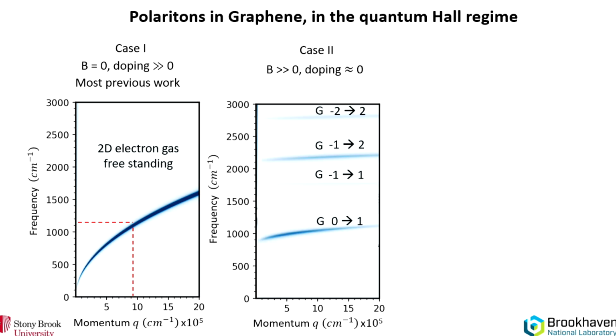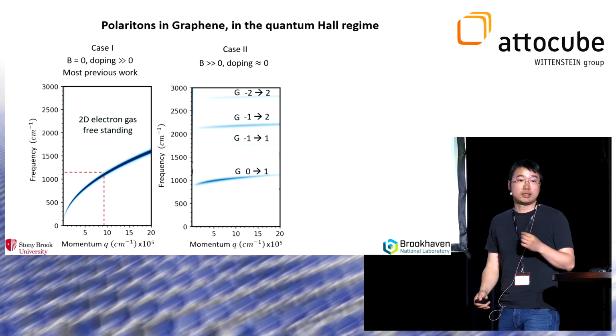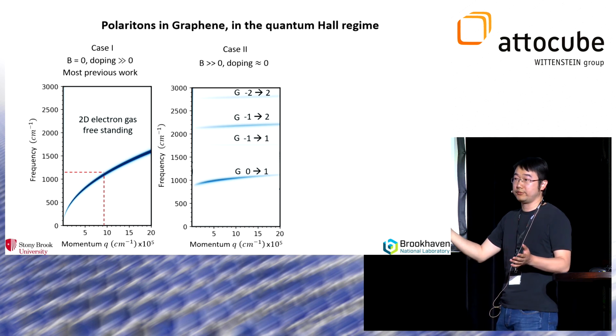So then we can go to the second case, where your doping is near 0, so that you are at the charge neutral point, so that you can actually access many-body effects in graphene. But now with applying magnetic field, you can access these quantized Landau levels due to the interband or intraband plasmon or magneto-exciton excitation, as I call it. And you can have 0 to 1 Landau transitions, -1 to 1, -1 to 2, -2 to 3, -2 to 2, and so on and so forth. And these Landau levels will scale with the magnetic field, right? This is a nice polariton that you can tune all the way from terahertz to infrared to visible by magnetic field.